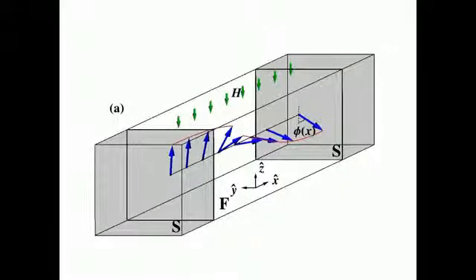If the magnetization profile is inhomogeneous, then the triplet may have a component protected from the magnetization by symmetry and propagate over long distances through the magnet as though it were a normal metal. This is called the long-range triplet component of the order parameter.